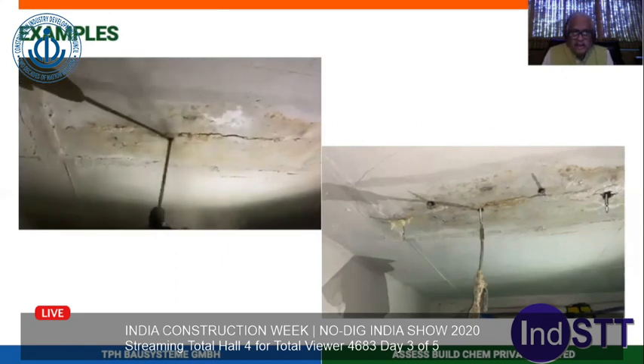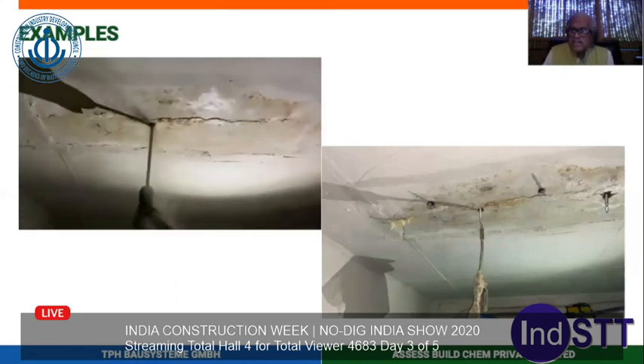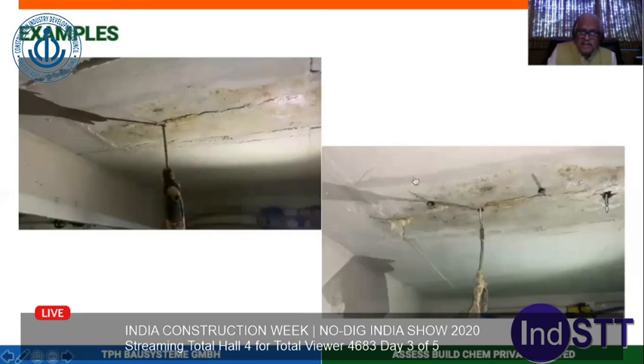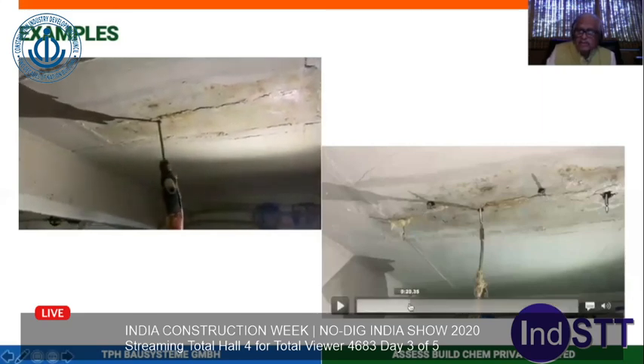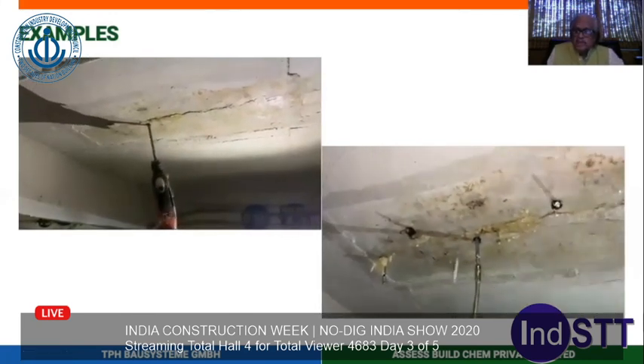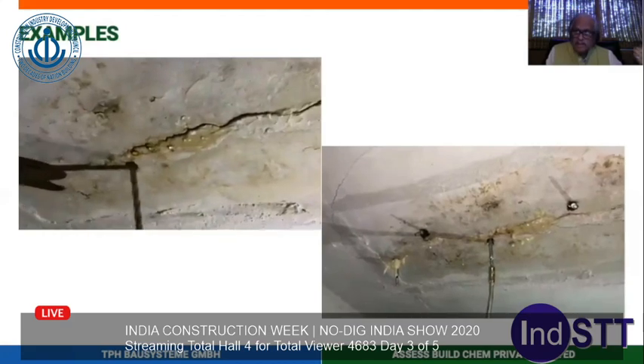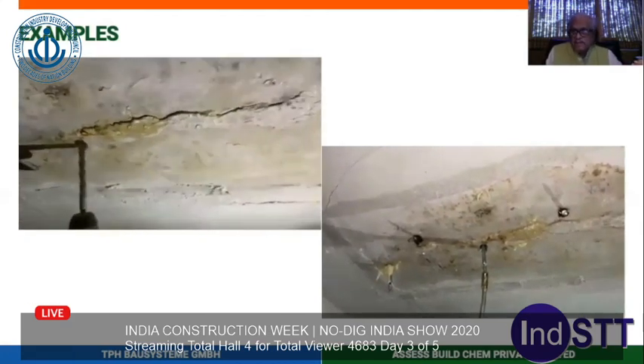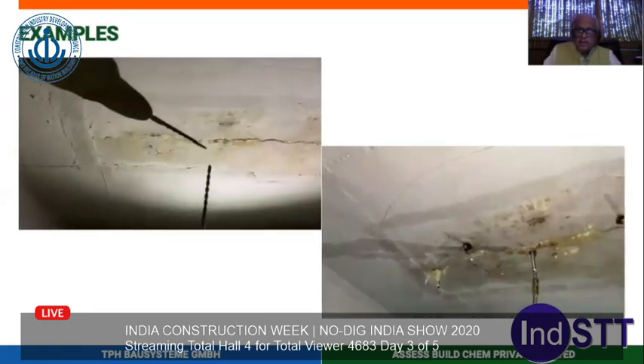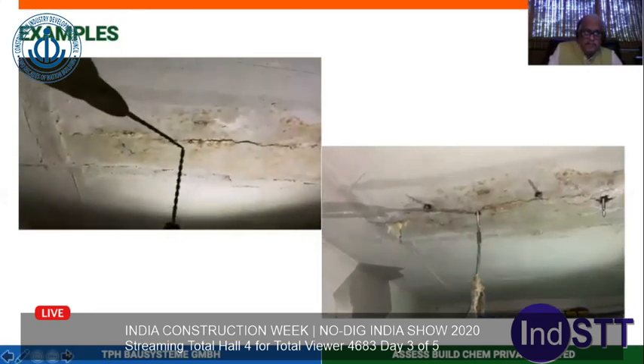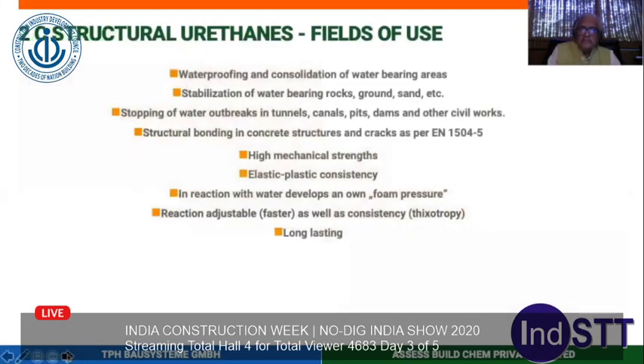You have to drill the holes at a 45 degree angle. You have to put the mechanical packers inside, fix those packers so that the material reaches the center of the crack, and then start injecting the material with proper machinery, with proper connections. Here you can use the ductile filling material. These are two component polyurethanes, but they also have limited structural capacity. Their aim is to seal these cracks. Their aim is not to increase the strength of the concrete, nor are these force transmitting injections. But these are also important in injections for podiums, for parking places.